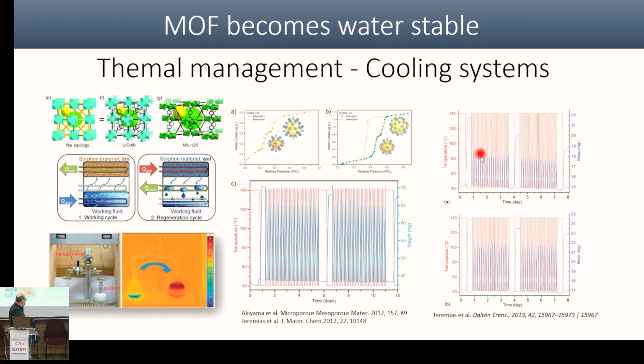This is UiO-66 functionalized by amino groups, and this is MIL-125, that structure, that is made by titanium oxocluster linked by terephthalic acid. Okay, so it looks decent enough for the use of vapors and the interaction and the in and out of water inside. And why is it interesting?